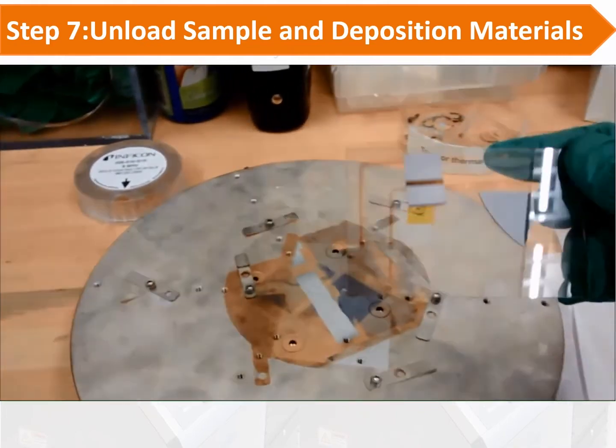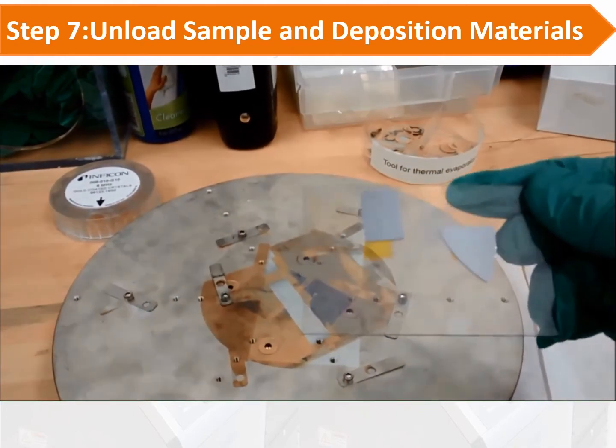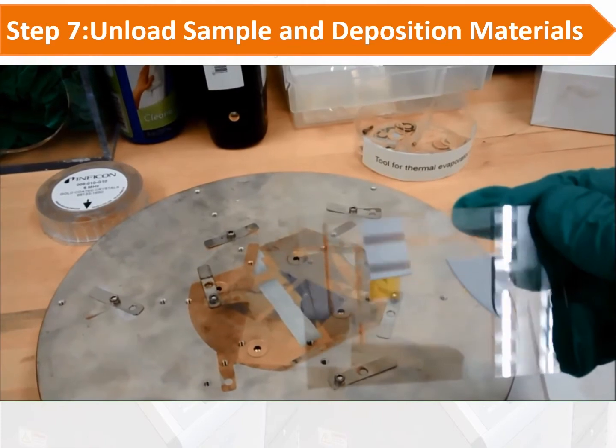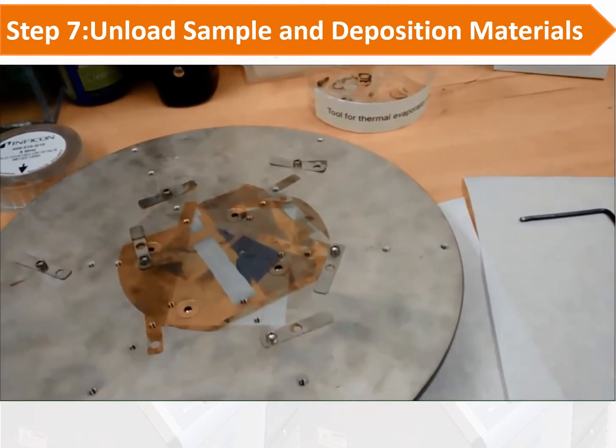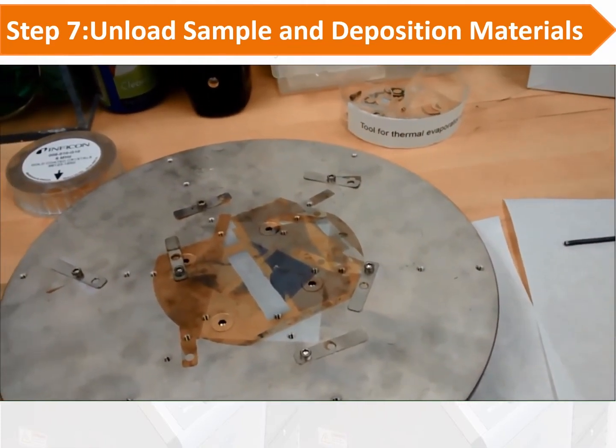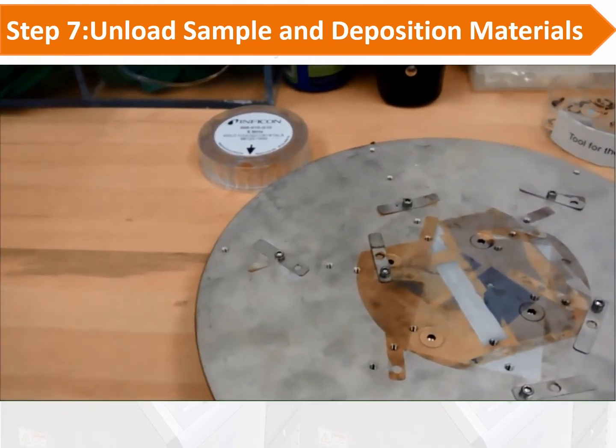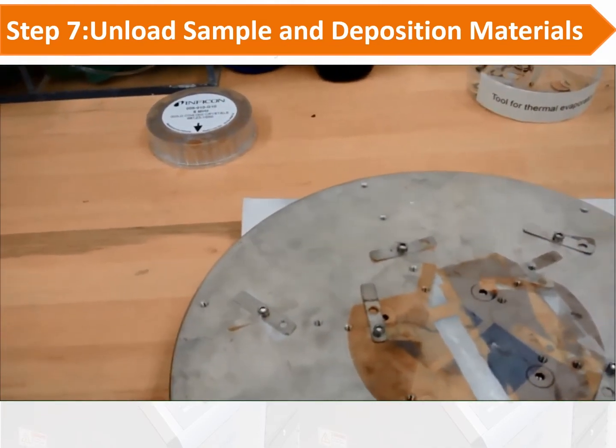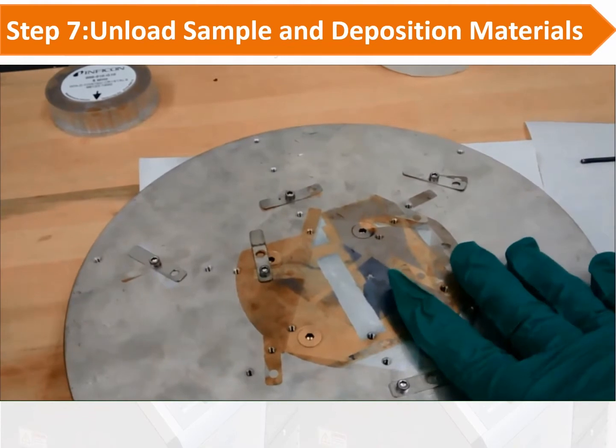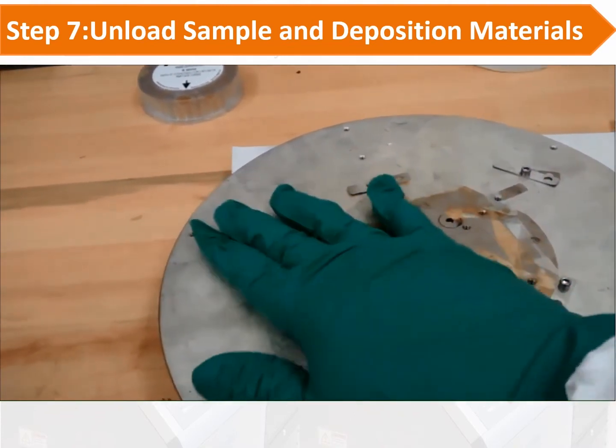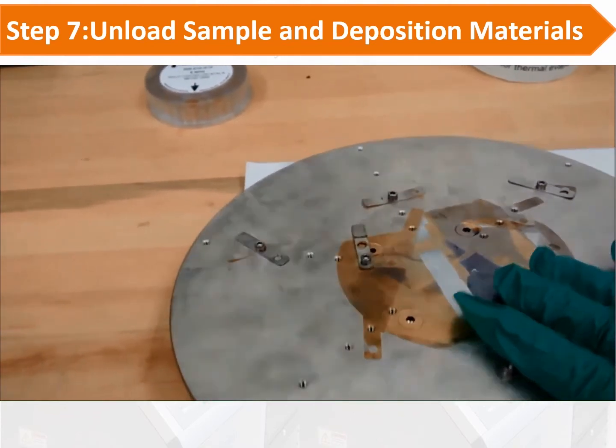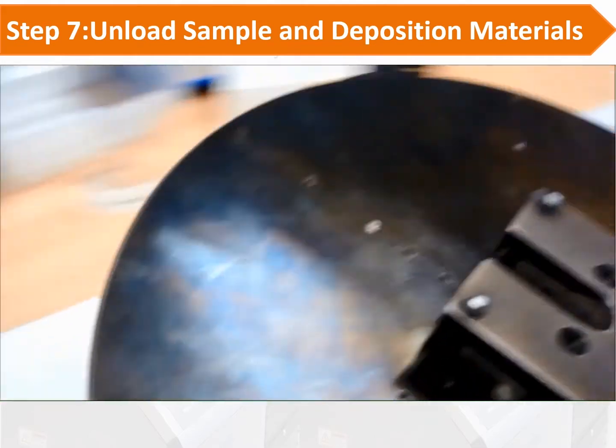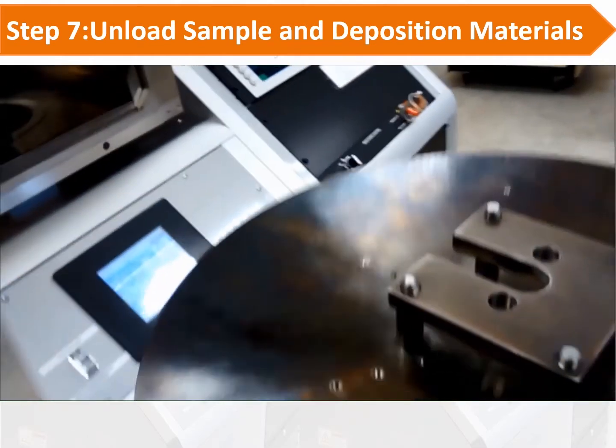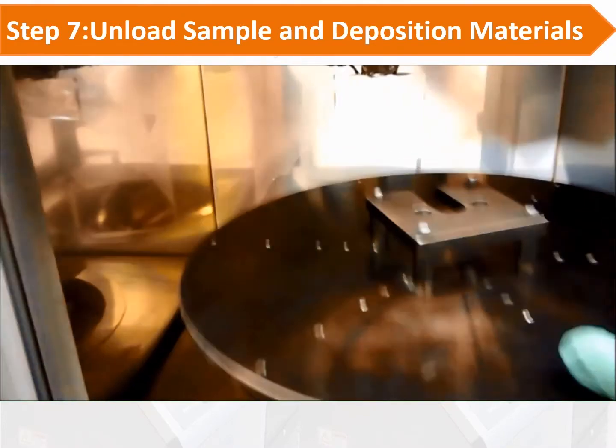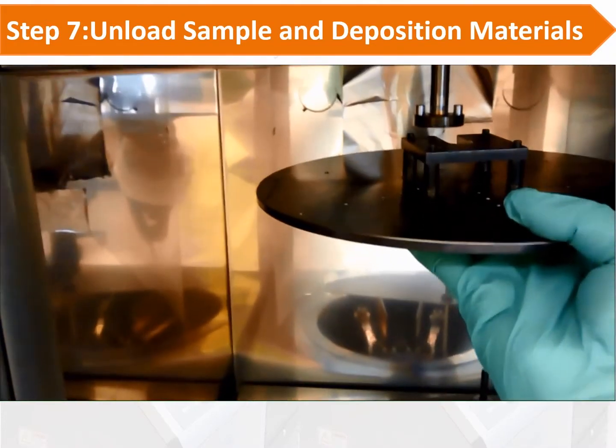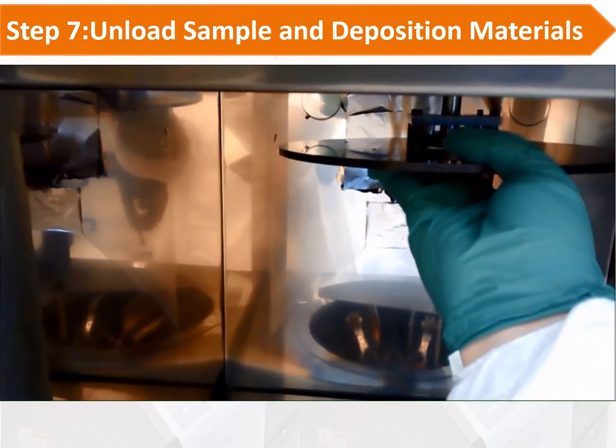This is the sample of the deposition. Please remember to tighten the screws on the sample holder after removing your samples, and do not leave any tape on the sample holder. And now you can put the sample holder back into the chamber. You can slide it in and put it back.